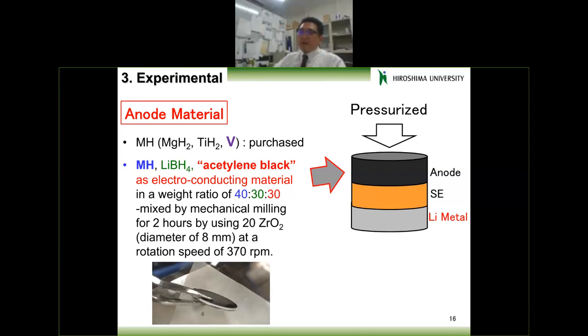Unfortunately, vanadium hydride is quite unstable. If we want to keep the vanadium hydride state, hydrogen pressure is necessary, so the hydrogenated state cannot be realized. So the starting material is vanadium itself. But magnesium hydride and titanium hydride are quite stable. So the starting materials are magnesium hydride, titanium hydride, and vanadium itself. And then something like this shape, tablets, pressurized together with the anode, the solid electrolyte, and the lithium metallic phase.